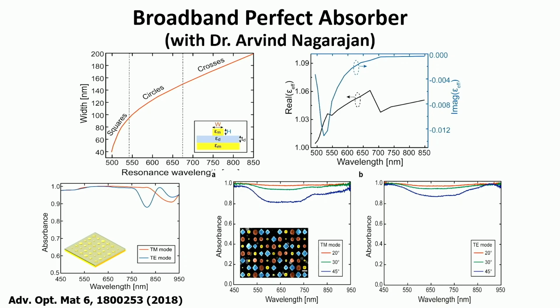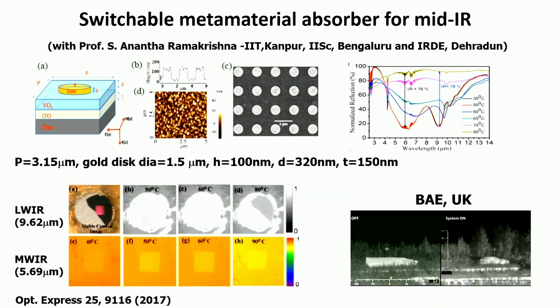Going back to the applications of these perfect absorbers, one thing we showed is a switchable metamaterial absorber. This is for the mid-IR region. Here you have patterned gold discs on top and vanadium dioxide, which is initially in a dielectric phase. As you increase the temperature, it goes to a metallic phase, and then it follows this metal-insulator-metal structure, which is suitable for the perfect absorber design.